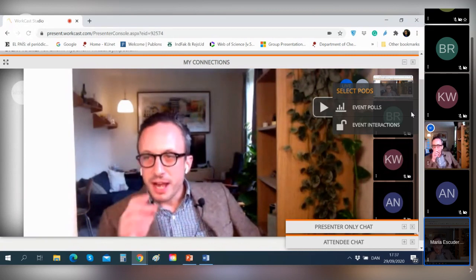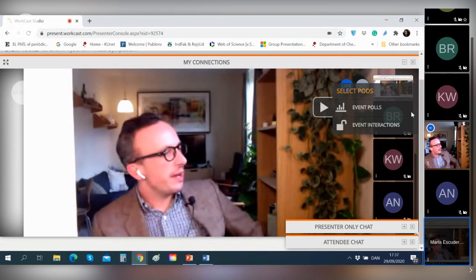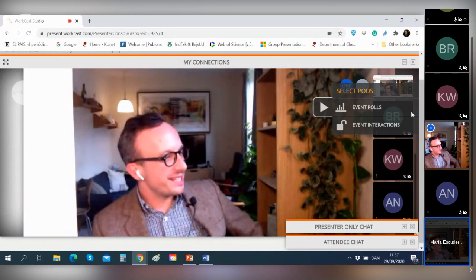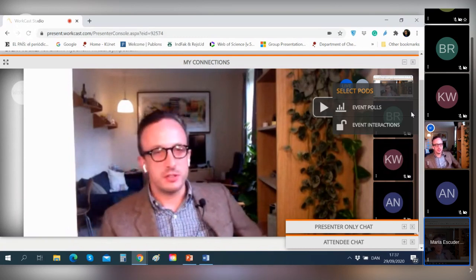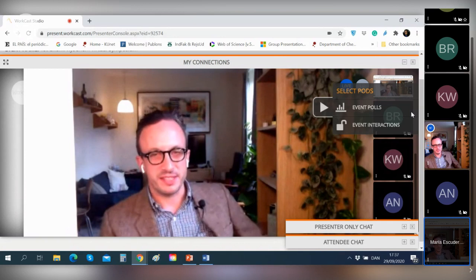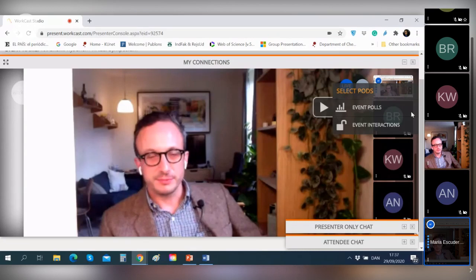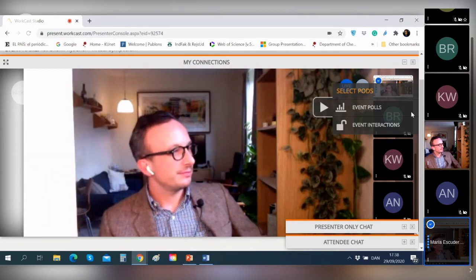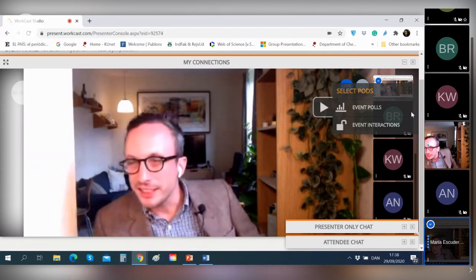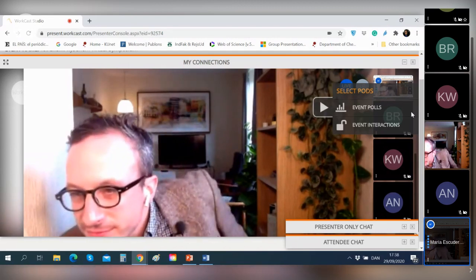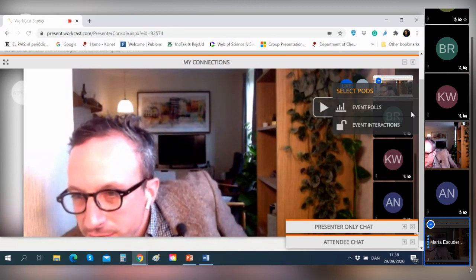So I have a quite brief question. I know Hari noticed that when you're doing CO absorption, it was really sensitive to temperature, so that in his group, they had to go to 0 degrees Celsius to do CO displacement. Did you observe this kind of sensitivity to temperature? As far as I am concerned, all the experiments have been done at room temperature, and all the results that I've shown are really reproducible. Sure. Okay. So with CO displacement, CO is weakly adsorbed, but you can displace the anion.